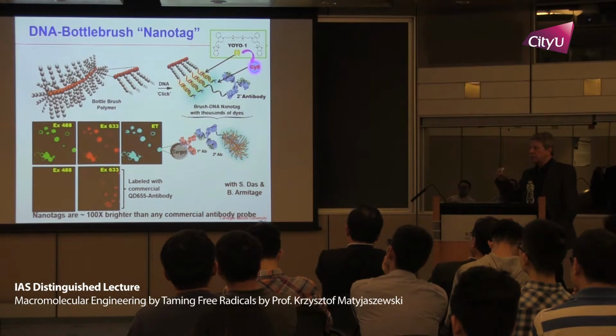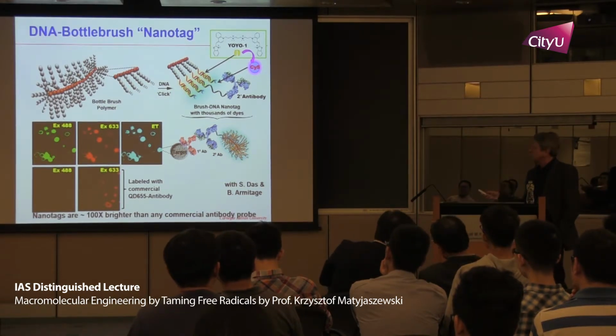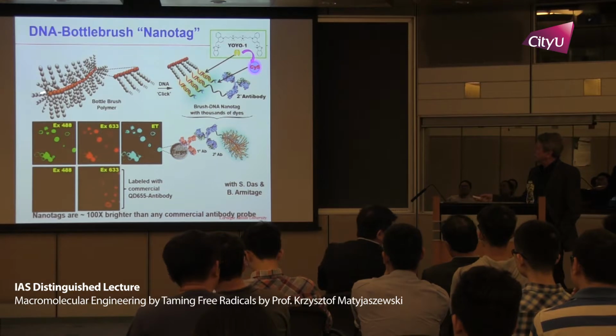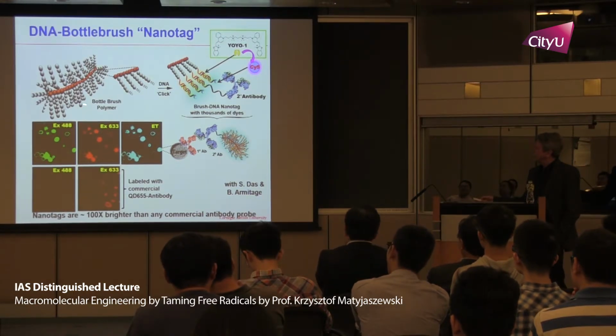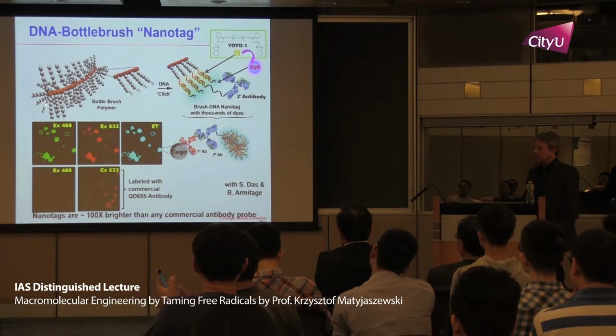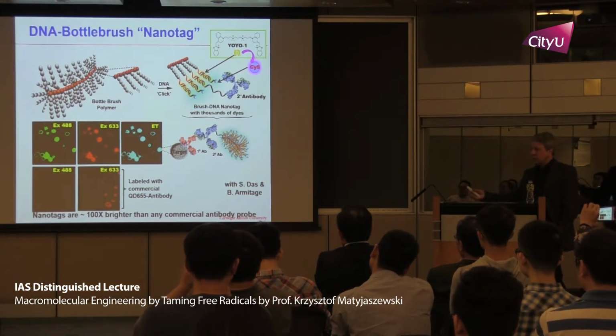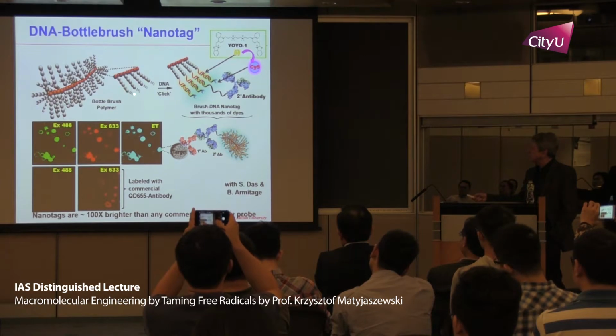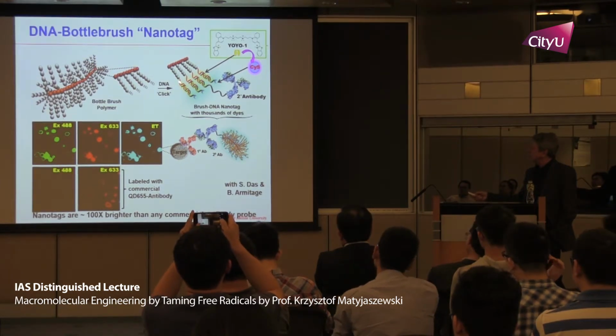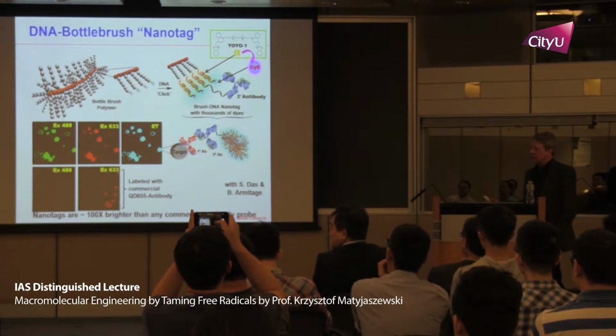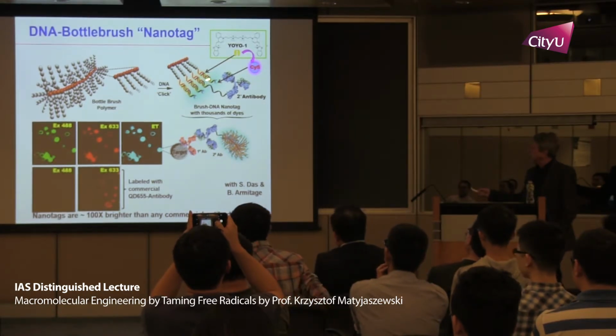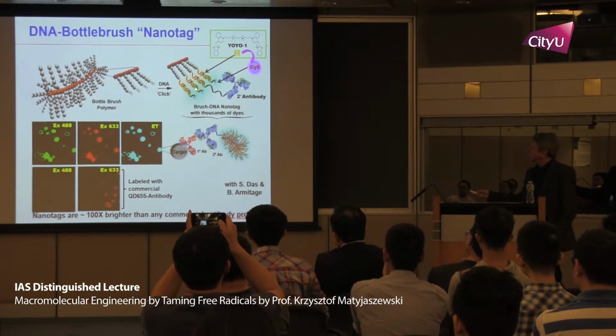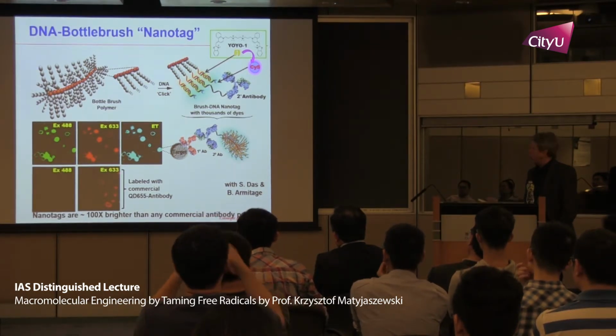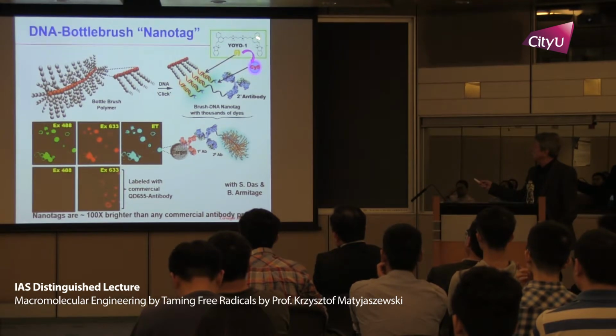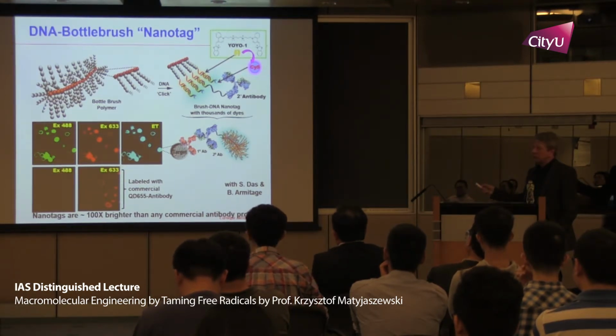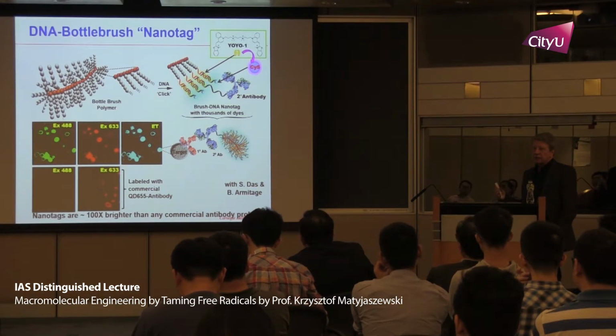Here's another example of what you can do by connecting this brush with nucleic acids. So we start with the brush, which is water soluble, and when it contains a bromine atom at the chain end, we replace it in a very simple way with sodium azide, bromine by azides, and then connect DNA with alkyne functionality to the brush. So you have now hundreds of these DNA bristles connected to the brush, and because it's negatively charged, you can intercalate this tetracationic YOYO-1 dye with thousands of these fluorescent brushes.